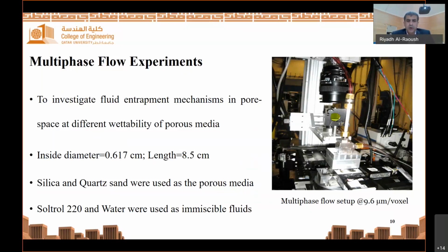We used different fluids, including oil and water, to represent immiscible fluids in the experiments, and to investigate the impact of wettability on the entrapment patterns of the fluids. Fractionally wet systems were obtained by combining various mass fractions of untreated and treated sands. The experimental cell was packed with porous media at different initial conditions.